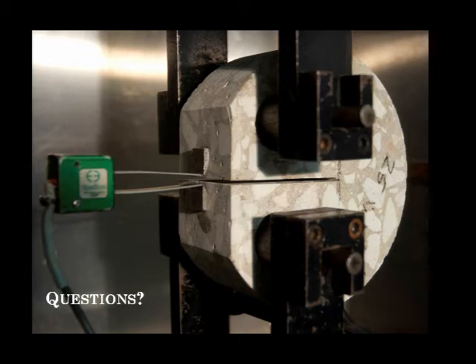Actually, this point came to my mind because we have tested some SEB samples and we have measured the fracture energy based on LLD displacement and also CMOD. They are quite different, around a 1.7, 1.6 ratio difference. So that's why I thought maybe. Yeah, I haven't done it, but apparently other people have done research into that. It's a possibility to look into.